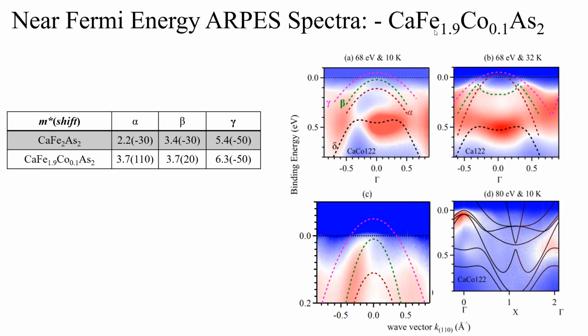So he has another comment. He says it is not clear if it is an underdoped or overdoped sample. It's difficult to say from here, because there is no phase diagram for this compound, I guess. To find whether it is underdoped or overdoped, we get the superconducting dome and see where the doping lies. If the doping is very close to the other end of the superconducting dome, then we call it an overdoped sample. And if it is close to the antiferromagnetic ordering and superconducting phase, then we call it an underdoped compound. But I don't know whether that kind of phase diagram is available for these compounds. If it is available, then we can say whether this compound is underdoped or overdoped. So if he knows, he can tell me.